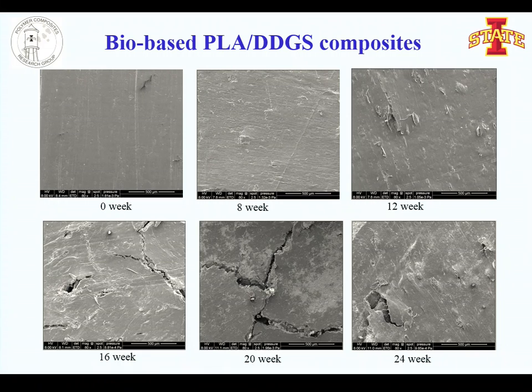The surface morphology, we have a smooth structure. After 8 weeks, this material looks okay. There is no degradation, but we have a huge crack, also deep cracking, after 20 weeks of degradation time.